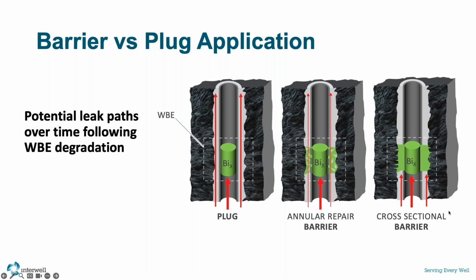And lastly, the cross-sectional barrier, which is what Rock Solid is. We go into the casing, through the casing, create a reaction that removes that casing barrier, removes all the wellbore elements surrounding it, gets to that borehole interface, and in that void space, we place our bismuth alloy sealing barrier element, made up of 3 phases. The bismuth alloy creates the seal. The sequesters are in the middle, encapsulated by that bismuth alloy, and the top is the anchoring system, the oxide or artificial rock, creating that rock-to-rock bond.